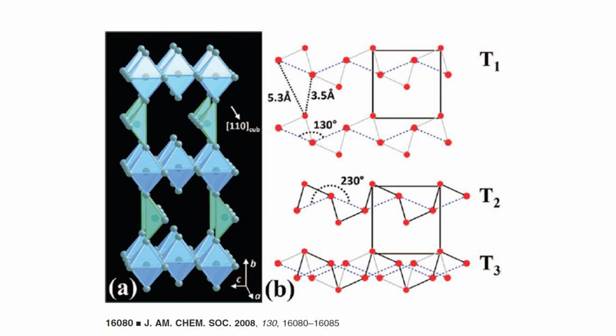Okay, and this is because you can see that tilting this tetrahedron will open or close the door of this solid. So our idea is that maybe there can be a phonon-assisted phenomenon. Imagine that there is a phonon in the solid that makes this flip of the tetrahedral oxygen. Okay, it's just a guess.